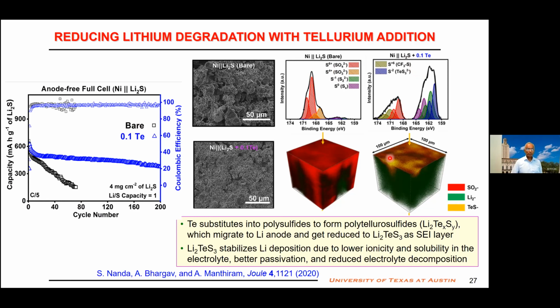Also, you get better morphology of the plated lithium. You will get better, smoother morphology than without having tellurium. So without tellurium, cyclability falls. As soon as you put tellurium, you can turn it around. I have data, but because of time constraint, I did not put everything here. But the main conclusion is this.